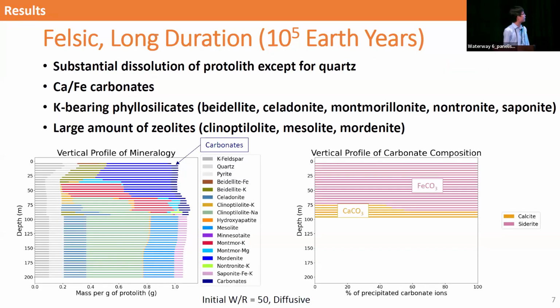And finally, we look at the felsic protolith with the long duration of alteration. The protolith was substantially dissolved, except for quartz and also pyrite, which did not dissolve. And the resulting carbonate was calcium iron rich with no magnesium content. A wide variety of phyllosilicates were produced, and many of them contain interlayer potassium ions. Also produced was a large amount of zeolite minerals.